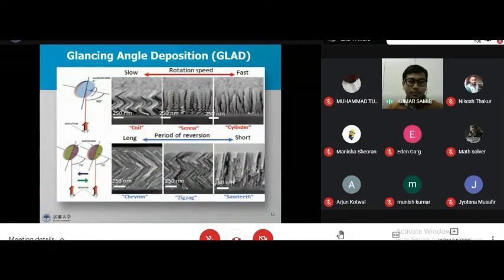And by controlling the rotation speed, we can make different nanostructures. If the rotation speed is slow, then we can get a coil type of structure, and if it's very fast, then we can get vertical columns. Also, if we rotate it in the azimuth plane by changing the direction of deposition, like by 180 degrees, we can get this kind of chevron zigzag structure, and this sawtooth kind of structure by changing the speed or period of reversion. So you can see different kinds of structures can be grown by simply changing the rotation and reversion.